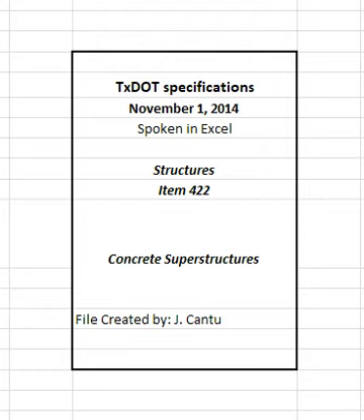The engineer will inspect the deck or slab for plastic shrinkage and settlement cracking after completion of final curing and within 5 days after curing mats are removed. Seal any noted shrinkage cracks attributable to contractor placing, curing, and finishing practices using gravity feed crack repair as directed in accordance with item 780, Concrete crack repair, at no cost to the department. Transverse cracks over interior vents in continuous slab units do not need to be sealed in this manner.